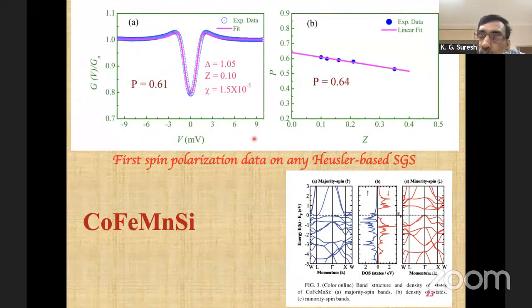So this is one of the first equiatomic Heusler-based systems where we have seen that spin polarization is there, and also it is a spin gapless material. That was the kind of attraction or the plus point at that time when we did this, almost 5-6 years back. It's a very interesting thing. A lot of people have tried this material because of this, and people have tried it in thin films and so on. They got very interesting properties, much more than what we got also. It has become a very wonderful system that way.